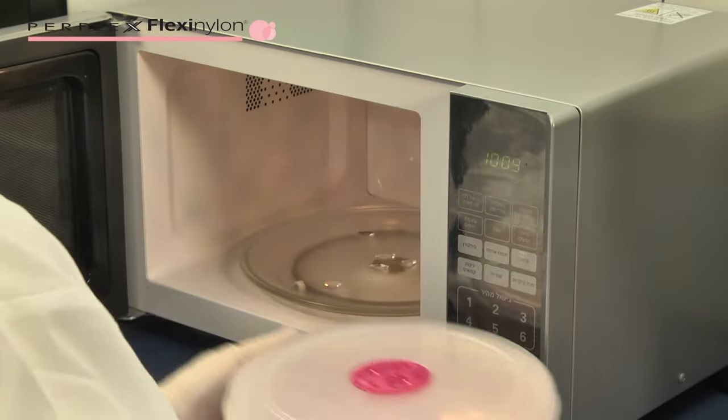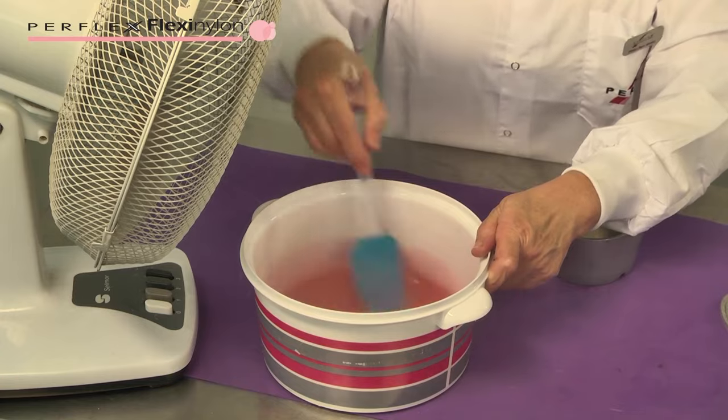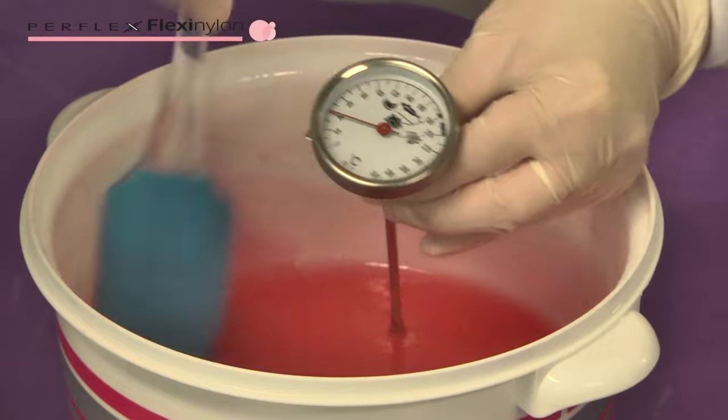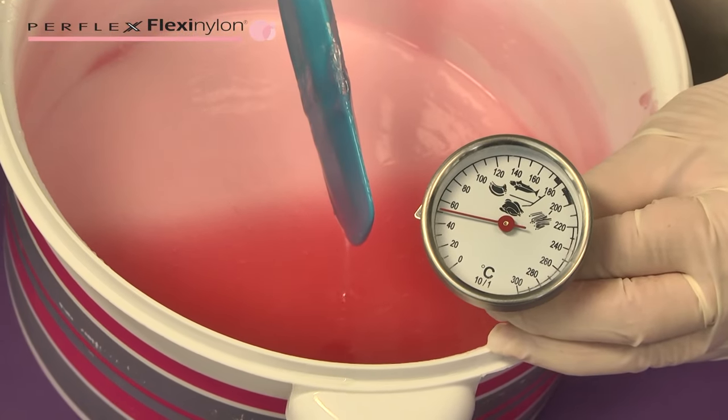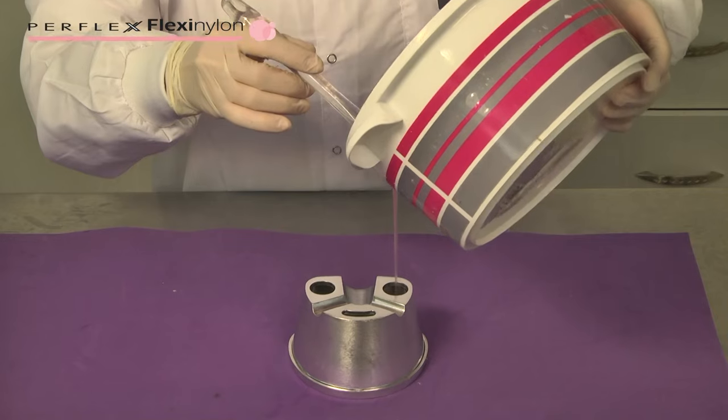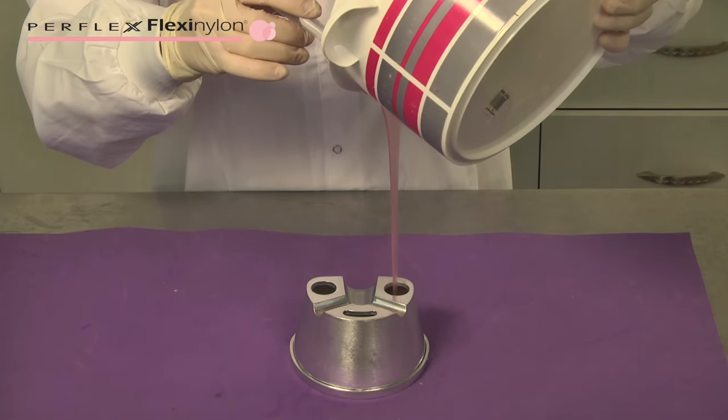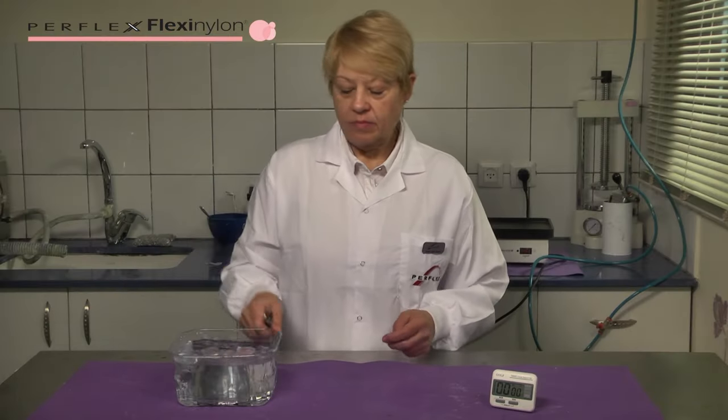Melt the gelatin in a microwave for 10 minutes at full power, and cool the gelatin by stirring with a spatula under a ventilator to speed up cooling. When the gel has cooled down to 52 to 57 degrees Celsius, or 125 to 135 degrees Fahrenheit, pour the gel and allow it to cool in the duplicating flask for 20 minutes, before placing it in a water bath for an additional 20 minutes for final setting.